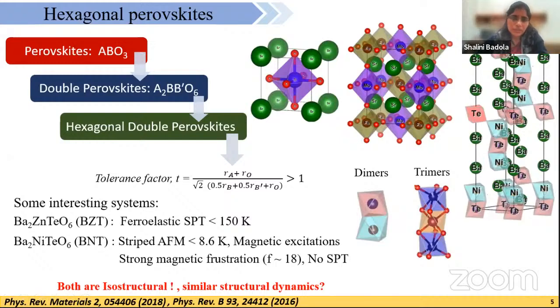For a tolerance factor greater than 1, hexagonal perovskites get stabilized, which comprise face-shared or corner-shared octahedra with reduced metal-metal distances along these face-shared trimers. This reduced metal-metal distance can be of importance because it can modify the electronic and magnetic properties of a material, which can help us in generating new quantum materials. So Ba2ZnTeO6 and Ba2NiTeO6 are two such materials which crystallize into hexagonal structures under ambient conditions. For convenience, I will refer to the zinc system as BZT and the nickel system as BNT from now onwards.